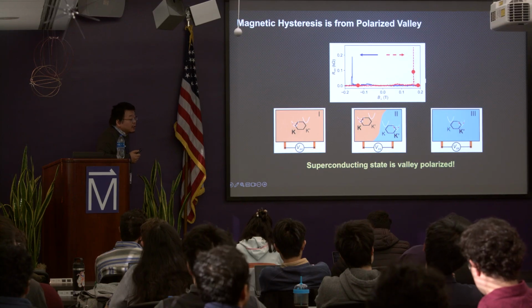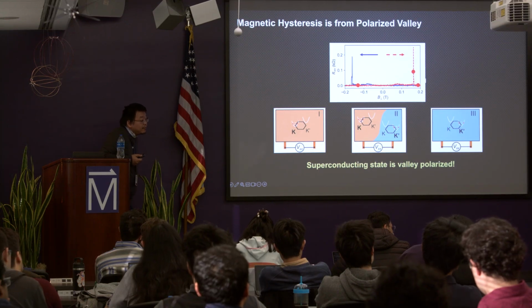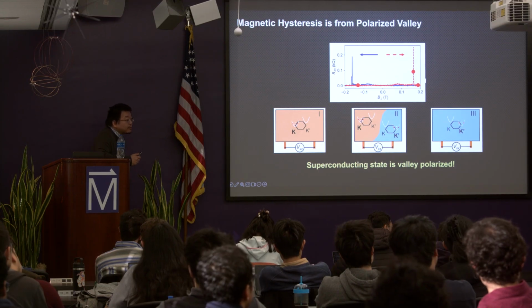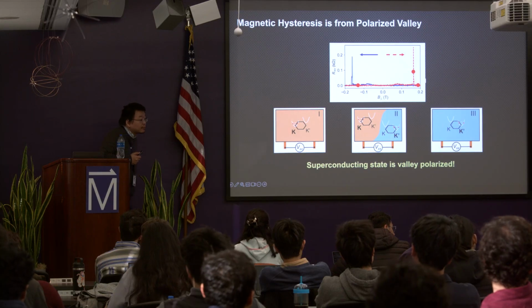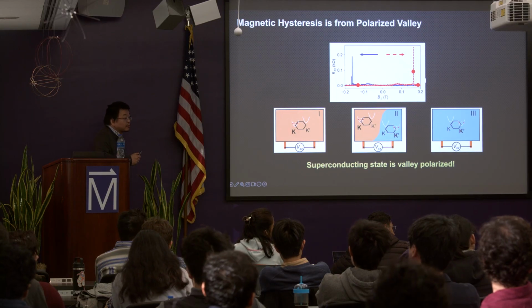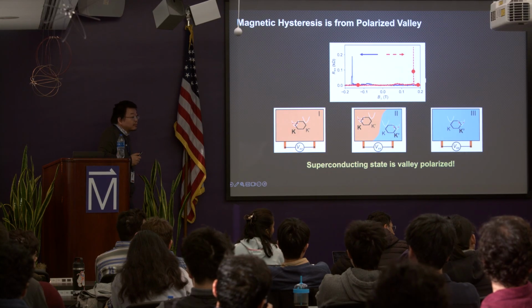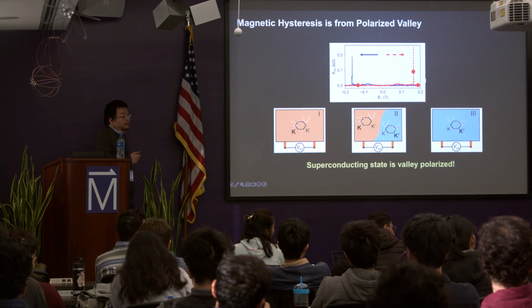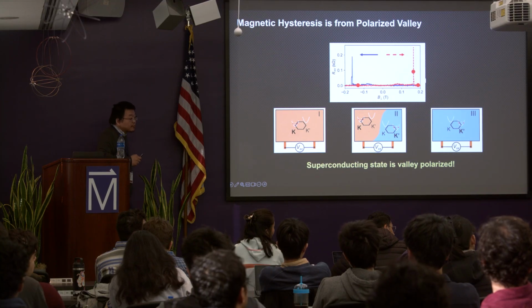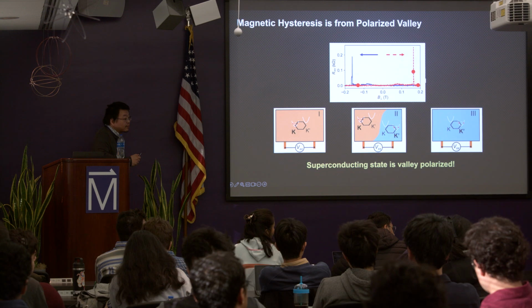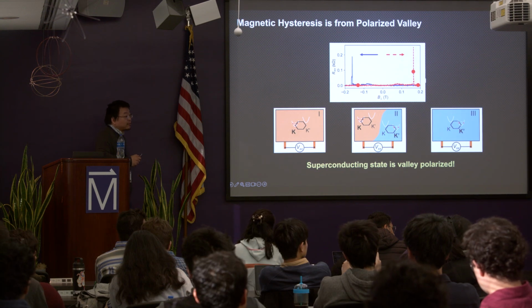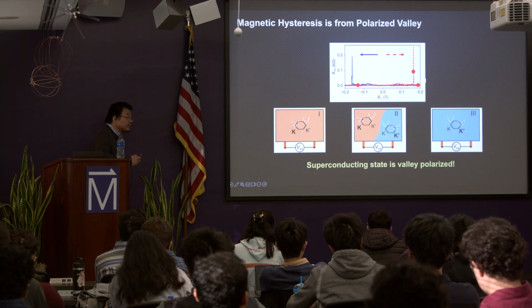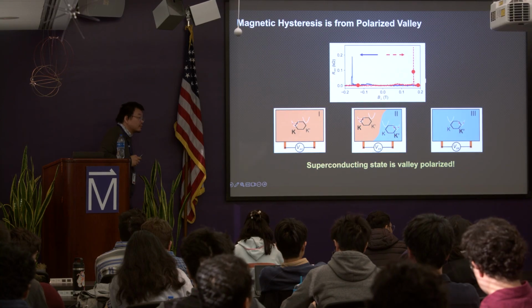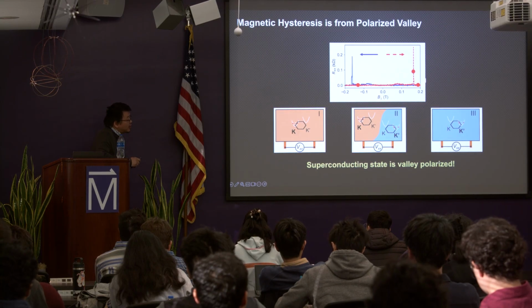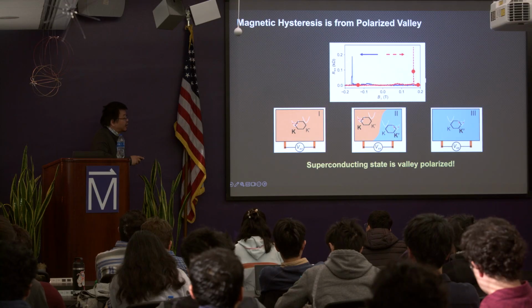So it seems to me there's another way. We have to kill the conventional superconductor. You don't get a simple penetration of field, like widening a vortex. You see nothing, and then all of a sudden, at a magnetic field, boom, you get field penetrating. Yep. And that, I think, would have the same phenomenology. Same phenomenology, but it will not have the magnetic hysteresis.